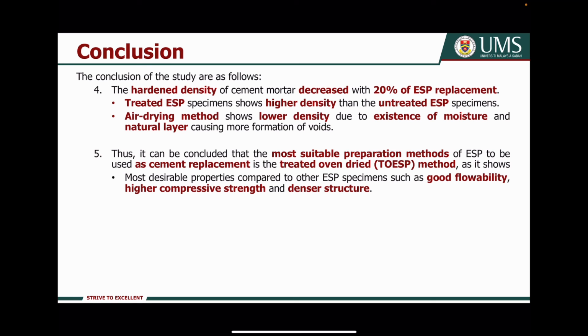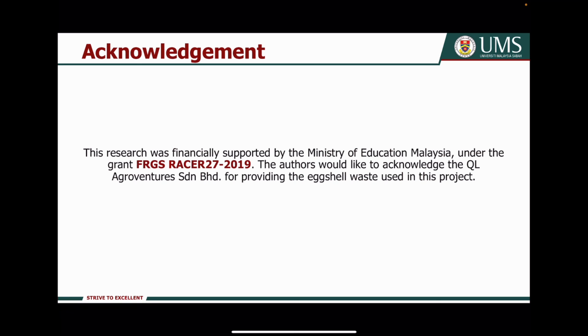For the hardened density, the treated ESP specimen shows higher density than the untreated ESP specimen. Meanwhile, the air-dried method shows lower density due to the existence of moisture and organic layer. Therefore, it can be concluded that the most suitable preparation method of ESP is the treated oven-dried method, because it shows the most desirable properties compared to the other ESP specimens, such as good flowability, higher compressive strength, and denser structure. This is the acknowledgement for my research.